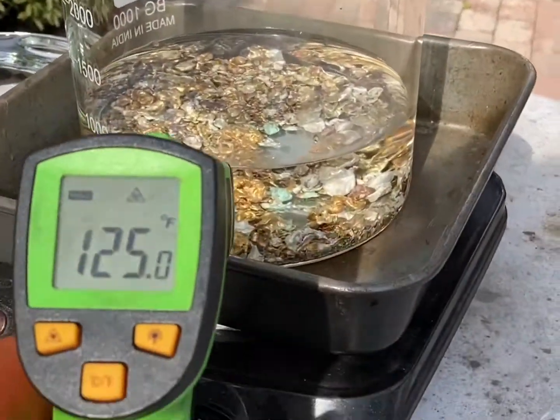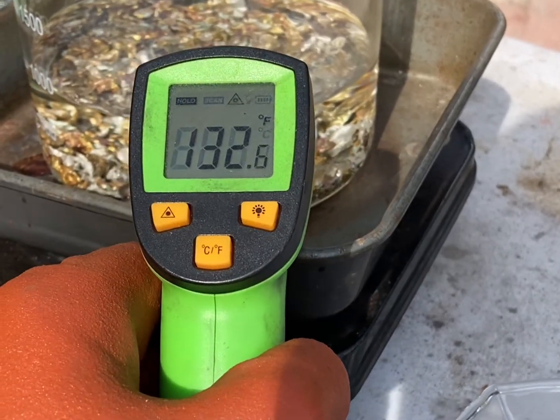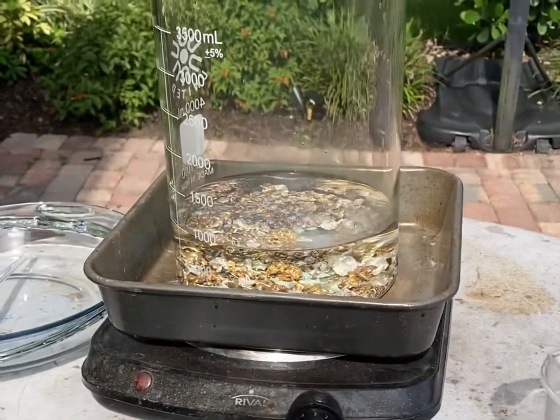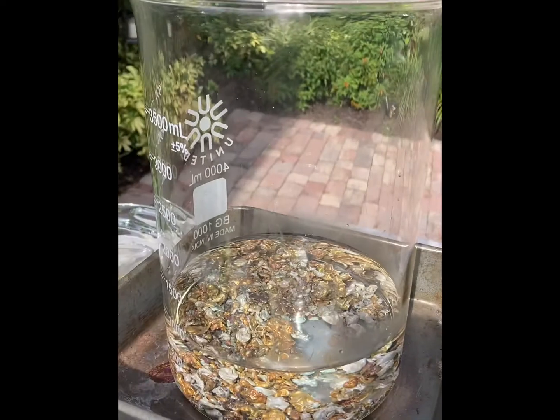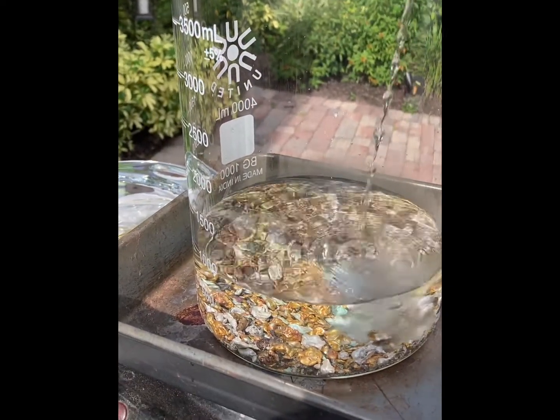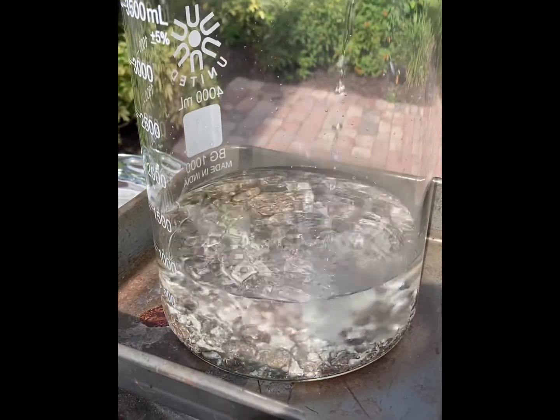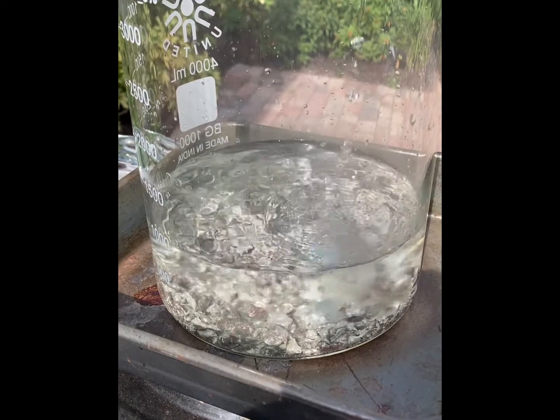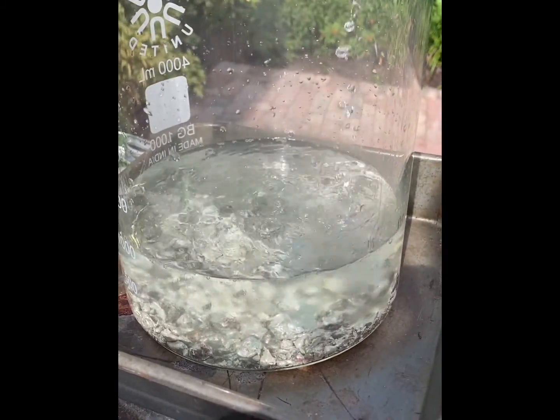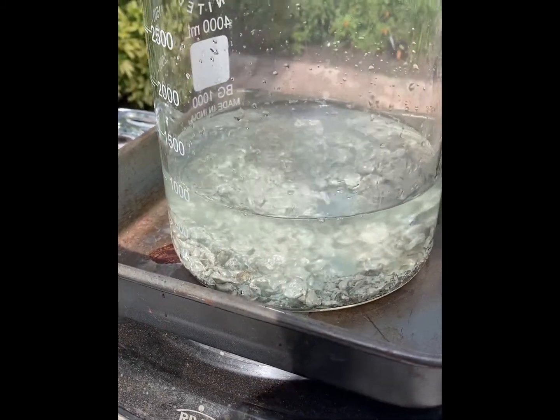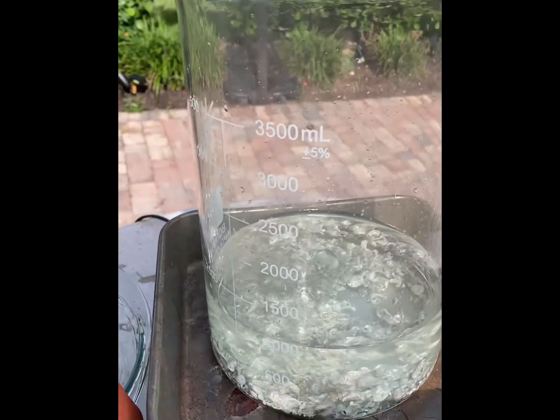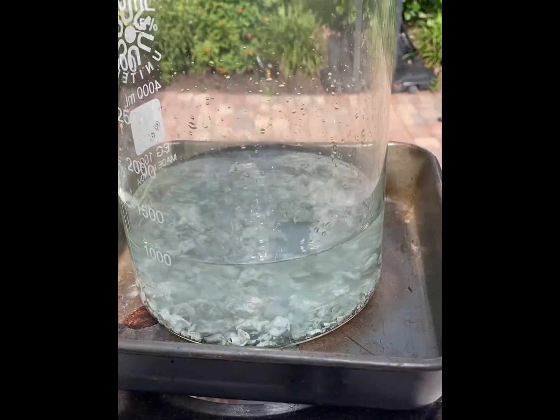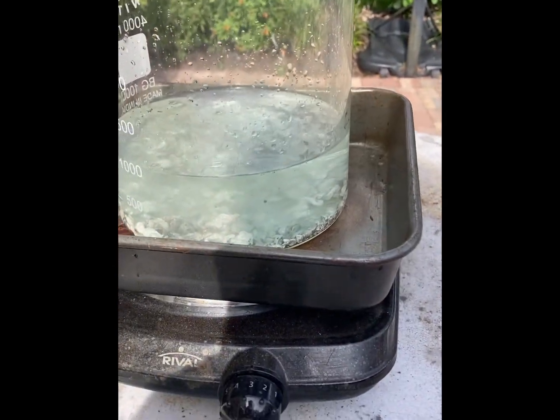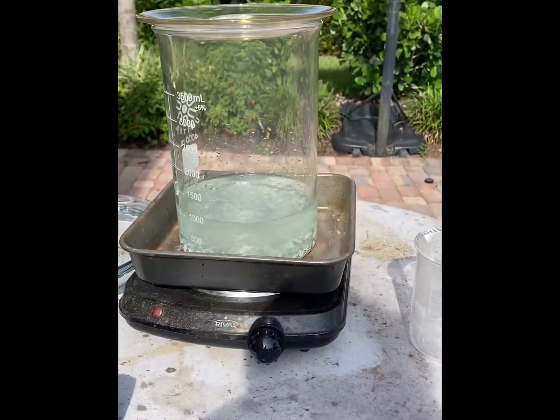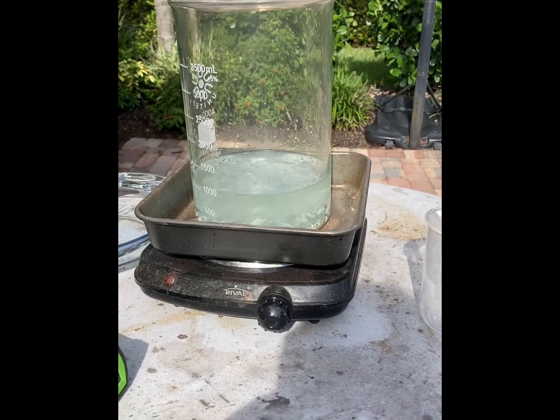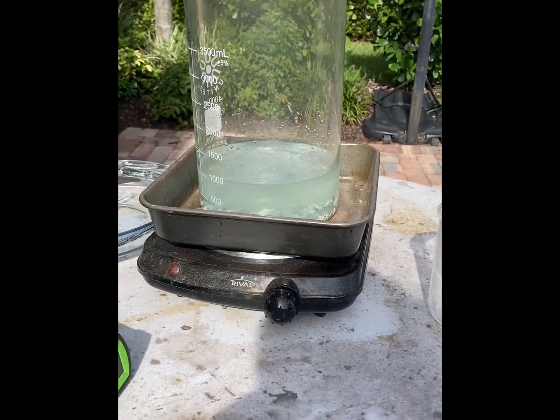All right, so now we're up to about 130, that's fine. So I'm gonna start adding the nitric acid slowly. So I got 100 milliliters of distilled nitric acid. You can see it immediately starts to eat away at the contaminated surface of that shot. That'll start reacting, and we'll let it cook for about an hour, hour and a half, and then start adding 50-50 dilute nitric acid and distilled water.